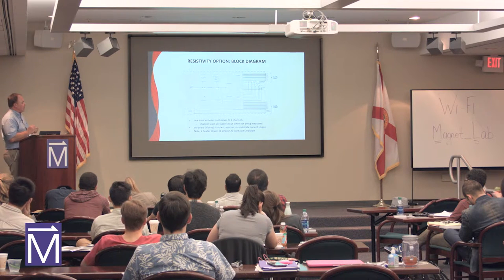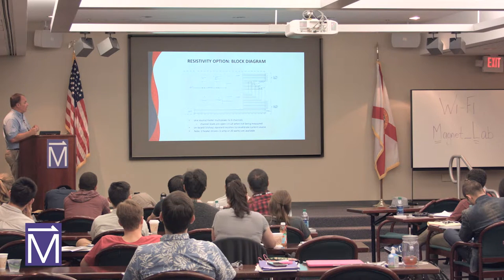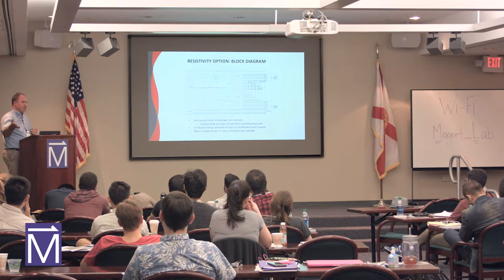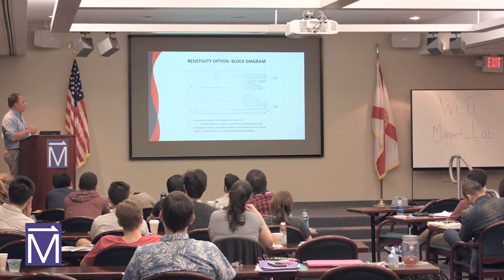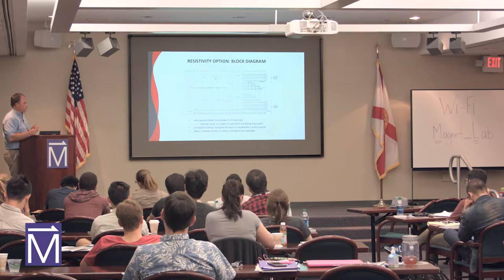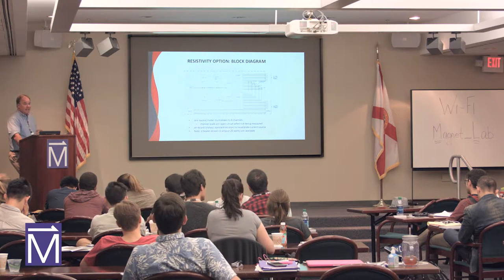of the resistivity option. We use a little multiplexer inside, and the leads are open circuit when they're not being measured. There are standard resistors inside the system so that we know the exact resistance, so we can know the current source value. And there's a couple of heaters in there, so this whole circuitry drives the heaters as well. So we've got a 1 amp or 20 watt circuit to put the heaters on to heat the sample space up.